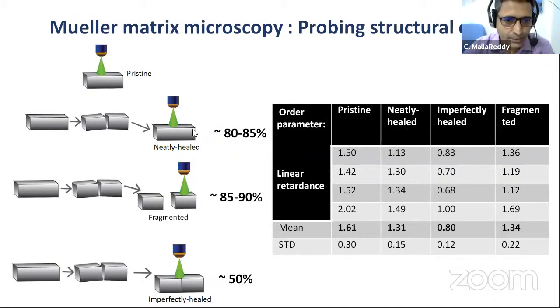Again, I have already explained this. If it is neatly healed, the crystallinity at the nanoscale, and don't forget this is nanoscale crystallinity, but for single crystal XRD, you don't see any difference. That would give you 100% efficiency, but at the nanometer scale you have 80 to 85% if it is neatly healed. If it is fragmented, where you just separate the two pieces and then do it, it is 85 to 90. And if it is badly or imperfectly healed, there is a big drop. So there is a penalty. To avoid this penalty, most of the time when there is a chance, it would go to a neatly healed state. That is the driving force.